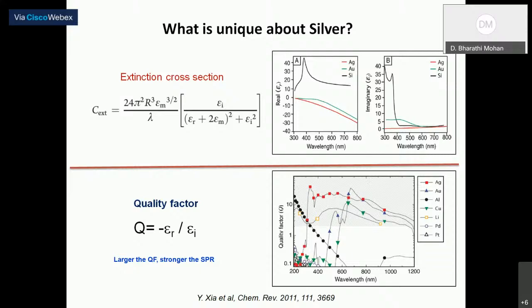So for any plasmonic material, the real part of the dielectric function should be negative, and at the same time the imaginary part should approach 0. If you look at the real part of the dielectric function of the three materials I have shown, silver has a negative value, whereas for silicon it is highly positive. At the same time, the imaginary part of the dielectric function of silver is approaching 0.